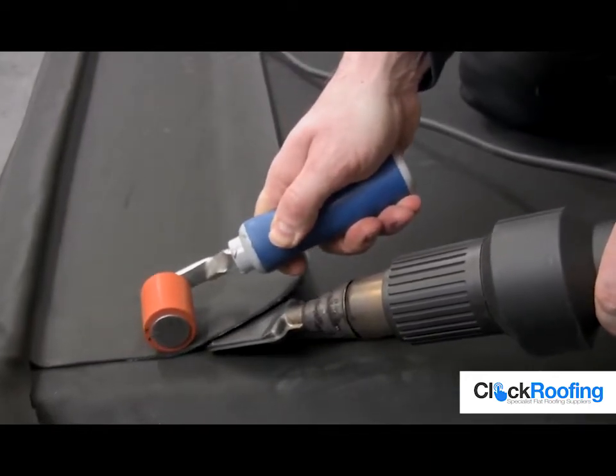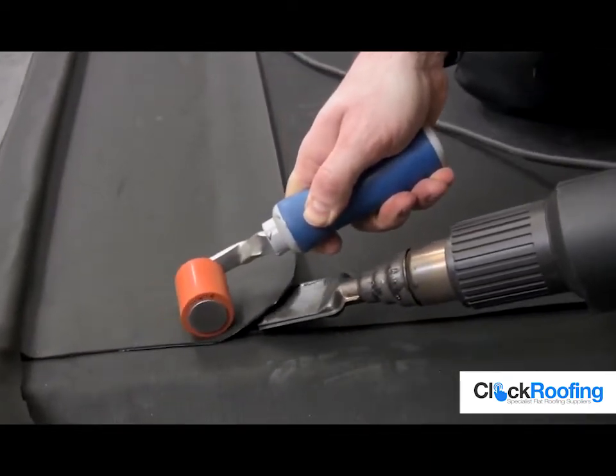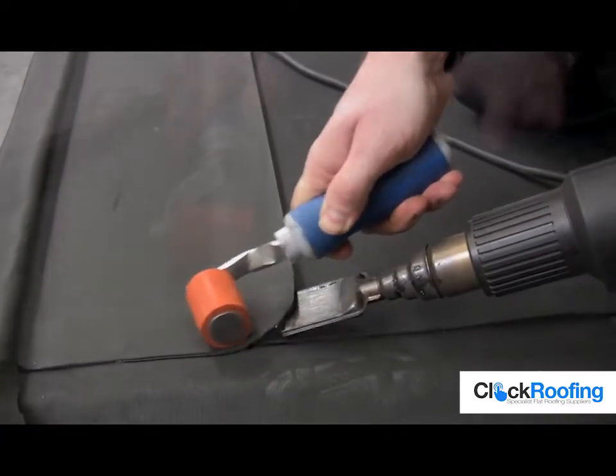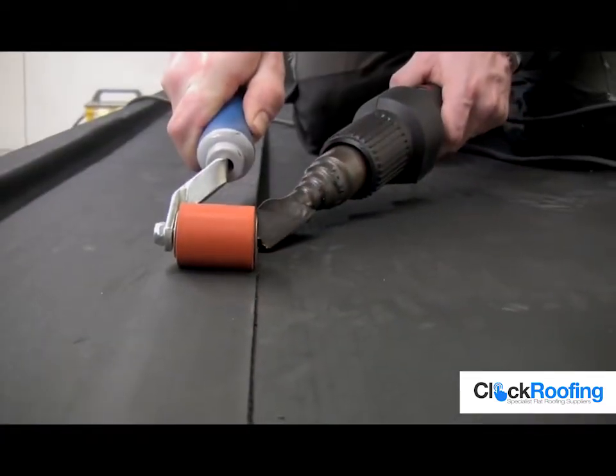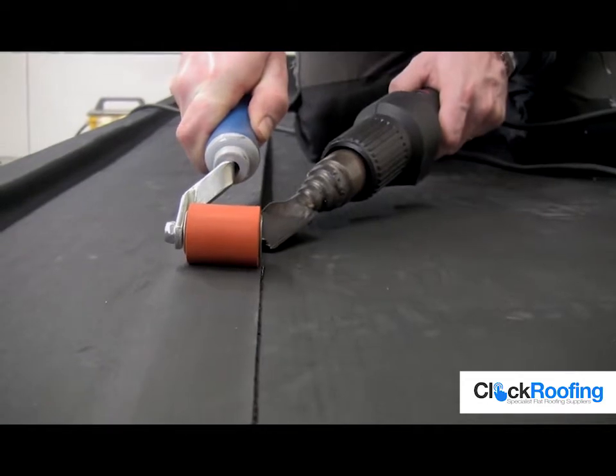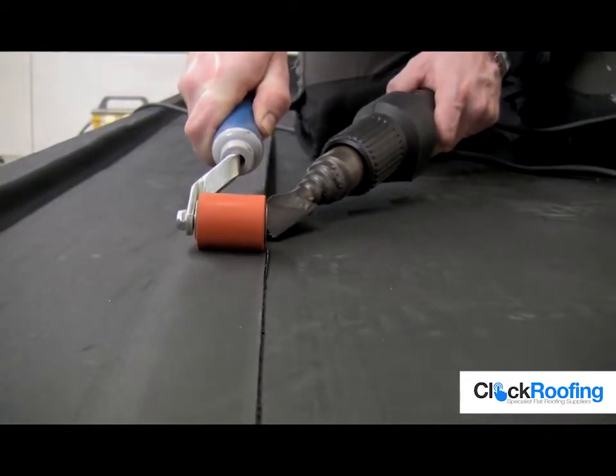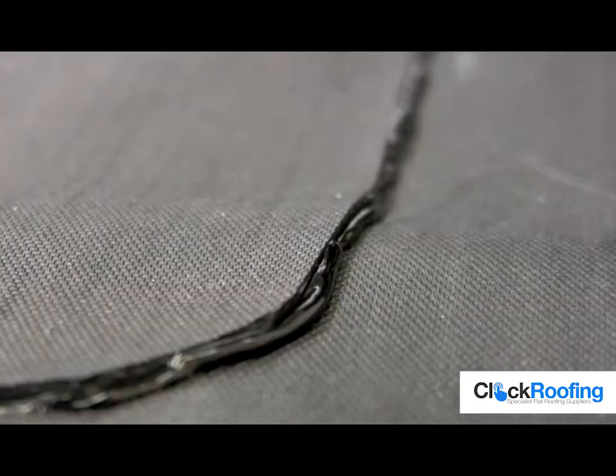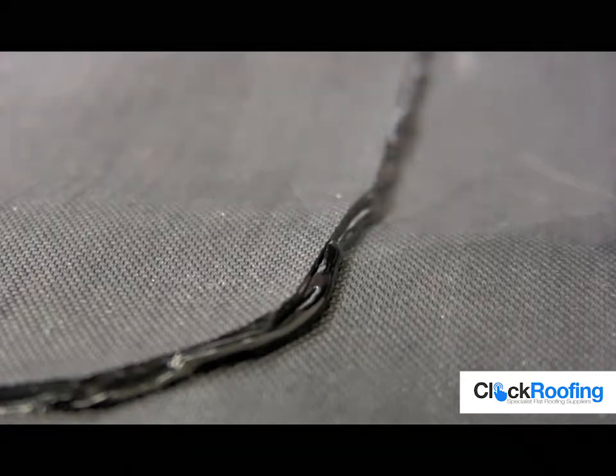Ensure a 2-inch or 50 mm gap is maintained between the heat gun nozzle and seam roller for a consistent weld. Excess pressure should not be required to create a bleed out. A good heat weld is indicated by a bleed out of the molten polymer bitumen from the bottom of the top sheet being welded.